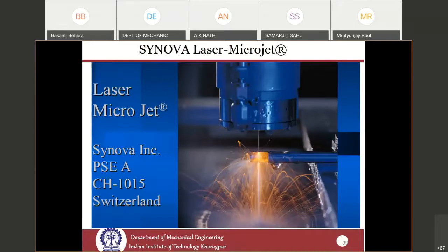Sometime in early 2000, one interesting development was done when high-powered fiber lasers and Nd:YAG lasers were developed. Here, through a very fine water jet whose dimension is in the range of around 50 to 100 micron, the laser beam is guided through this and then allowed to fall on the workpiece to do the cutting. Since the refractive index of water is 1.3, more than air whose refractive index is 1, at a proper incident angle when the laser beam is focused, it can be guided like a waveguide and carried without much loss.